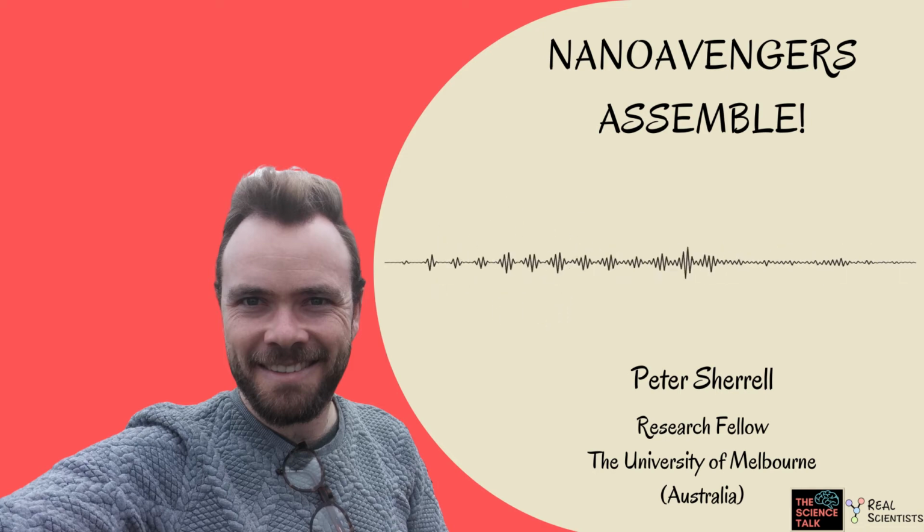So, well, an electric current across the graphene. What that did is it made the cells grow much, much quicker and very differently. So we saw a lot of what's called neurite outgrowth. What that means is you get little filaments coming out from the cell that show the cell's really, really happy. So we could see these networks of cells growing together much, much quicker and, I guess, yeah, happier, for want of a more technical term, on the substrates with the graphene and the electrical stimulation.